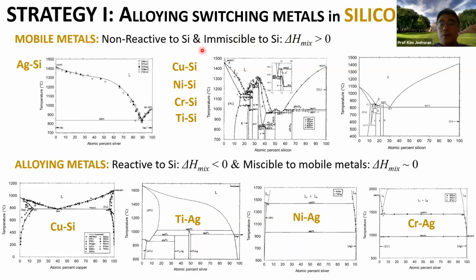The condition for doing this is that the metal needs to freely move around inside the silicon. To do so, this metal does not like to form a compound with the silicon, because if this metal forms a compound with silicon, then it will form a very stable compound. It cannot be dissociated, meaning that you cannot reset this device. Then what kind of metal is perfect for that? The perfect metal is one that does not have any solid solubility with the silicon, meaning that this material does not